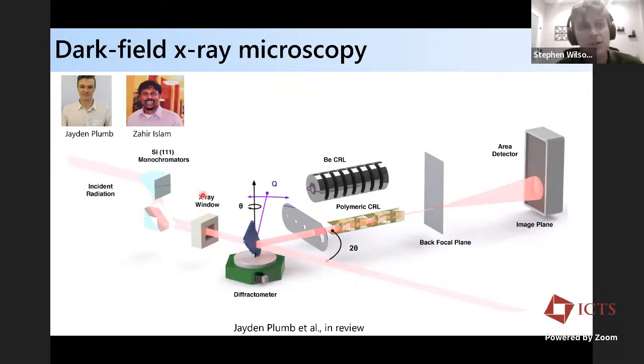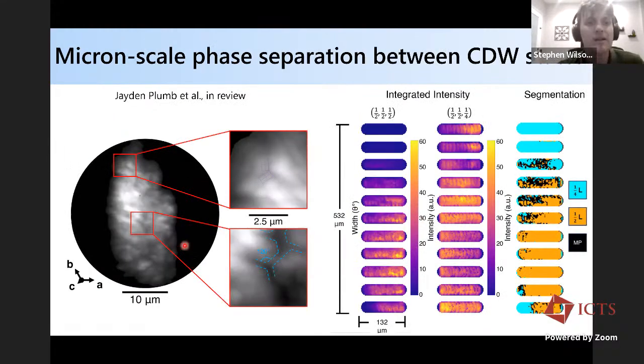And so one of the techniques you can use is so-called dark field X-ray microscopy, which is basically using a microscope to look at Bragg peaks and to see where the Bragg scattering comes from in real space. And so doing that, you can look at just the structure. Okay, so this is not a charge superlattice peak. For instance, this is just a primary peak in the lattice. And you can see there's actually fine structure in the lattice, which is just coming from structural defects. And this is nominally a pristine crystal. And so you can see line defects, and along those line defects, we can see structural domains form.